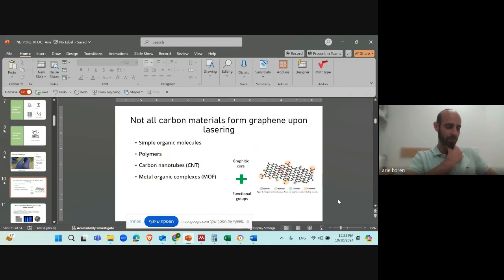Okay. Now we have to keep in mind that not all carbon precursors, not all carbon materials can undergo this graphitization process with the laser. So in fact, there was one lab of James Tour that published a paper with 15 different polymers, and only 2 of them could generate graphene. And it turns out that what you need in order to form graphene is a beginning, let's say, a seed of graphitic or aromatic carbon, and this is what the first precursors were, GO, graphene oxide, and a lot of polyimides because you already have these aromatic rings,